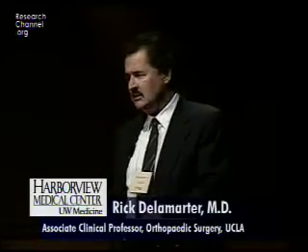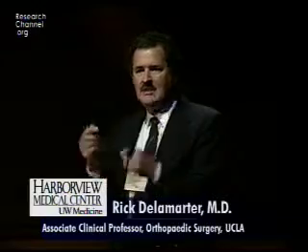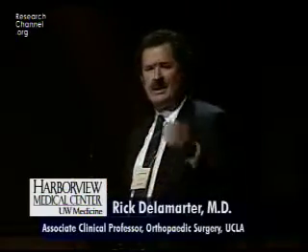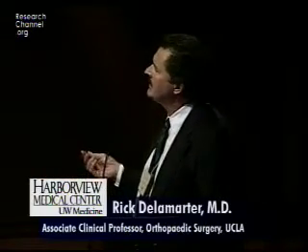This is clearly different than hips and knees. We don't wear the polyethylene in the lumbar spine or the cervical spine — it's a different joint, it doesn't have the same forces. There's no synovial membrane, and that probably has a lot to do with why the polyethylene is not wearing. A lot of people ask when we'll have to go back and change that poly. European follow-ups at 15 to 16 years show they haven't had to go back, and the wear is very minimal.